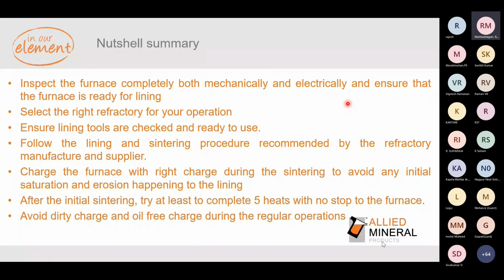Charge the furnace with the right charge, as we discussed, like returns first and pig iron and steel next, to avoid any initial saturation and erosion happening to the lining. After the initial sintering, try at least to complete 5 heats with no stop to the furnace, because there are people who shut down the furnace immediately because of production capacities, which is not recommended because your hot face formation is not yet completely formed and matured enough. So try to take at least 5 heats before you shut down a furnace. Avoid dirty charge and oily charge during the regular operations.